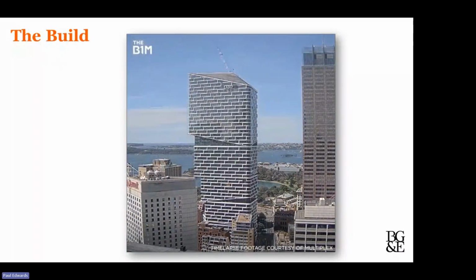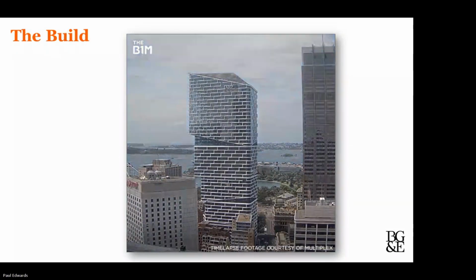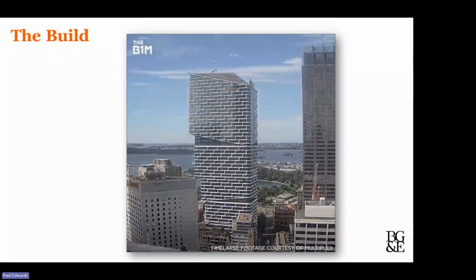Now, I didn't say, after having gone through in a little bit of detail how the core walls were found to be significantly weaker than desired, and how this building, as you've just seen in that time lapse, changed significantly, leading to significant changes to the lateral load on the building, how those areas were resolved. What happened was that for those two key floor areas, levels 27 and 28, they were identified as needing steel jacketing reinforcement. So they're basically steel plates applied to those core walls, but only on levels 27 and 28.